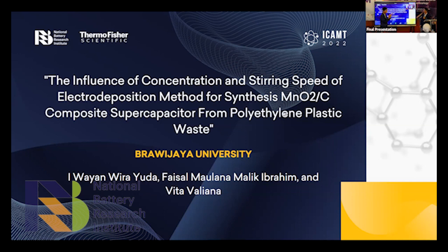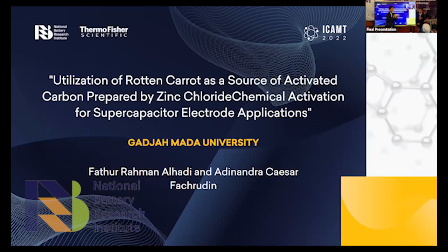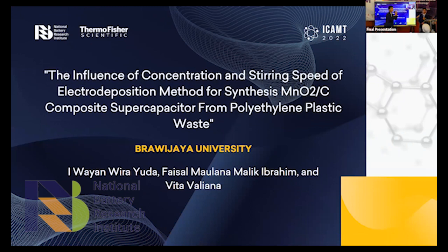Any chemical reaction? Okay, maybe from physics, as we know, when we take it through thermal degradation in the range of 450 degrees Celsius for 2 hours, we can get the carbon, but it's still not activated. It's still just a carbon. From our research, we get the black carbon, and after that to activate it, we immerse it in zinc chloride solution for 24 hours, so it can open the pores of the carbon, so it becomes activated carbon. Yes, to create porosity from the carbon.